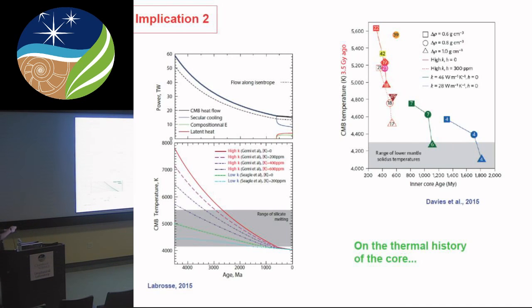So you have to have a very hot core in order to reach that value, that is the core temperature at the CMB today here. So this is how much heat you need to remove in order to get that pattern, in order to get the magnetic field working using the thermal convection mechanism. Of course, this value can be moderated if you put a lot of potassium in the core, which is a source there, but it's not going to be such a high amount. And this is for a lower conductivity value, because you're certainly aware that there is a lot of controversy about the conductivity value in the outer core.